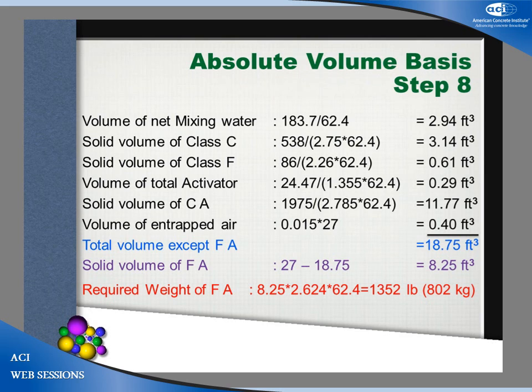simple absolute volume. We know the quantity of all the ingredients except the fine aggregate, so put everything on the absolute volume basis. This is our US system I gave in this slide. So divide by the specific gravity and 62.4, that will give you the volume in cubic feet. So 18.75 is the total volume we got except the fine aggregate. We also considered the entrapped air at 1.5%.